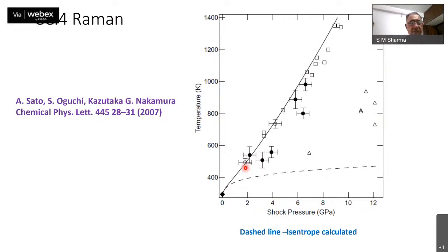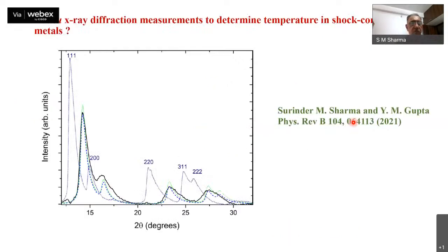But then, because Raman is a very weak signal, if one requires to measure very high temperatures, which can happen under high compression, there's a lot of background scattering which will come from the infrared radiation. So signal to noise ratio becomes very poor, and its precision actually dwindles.